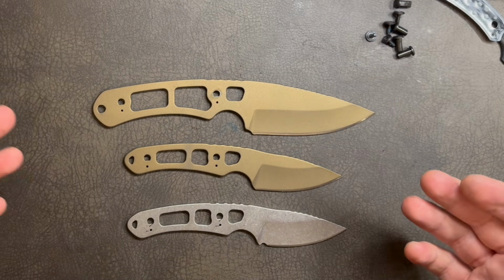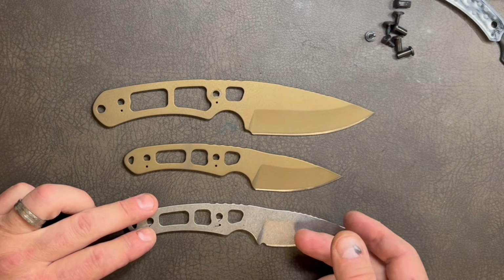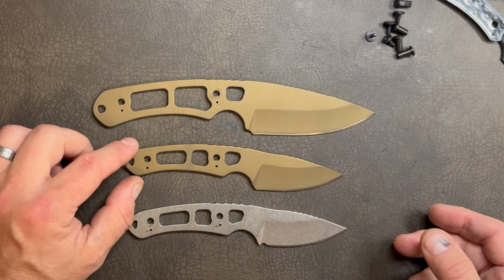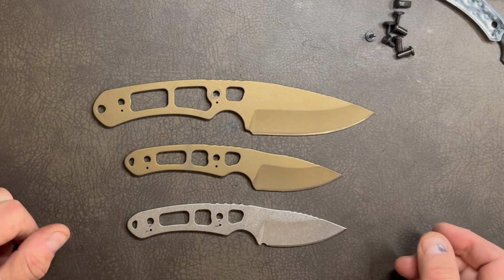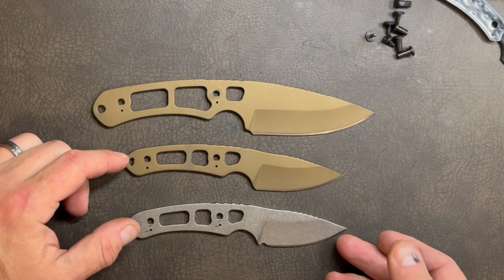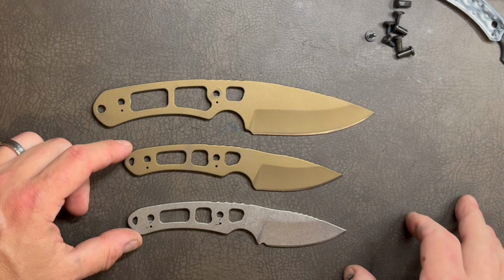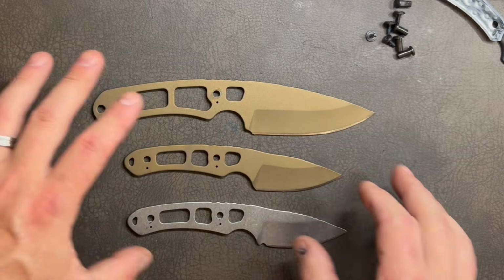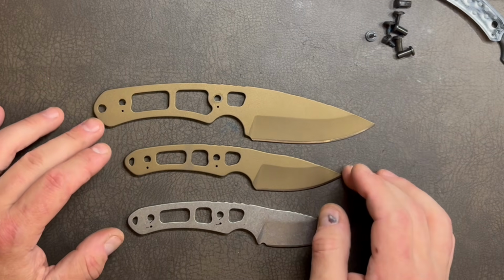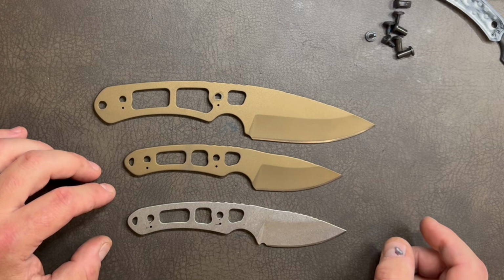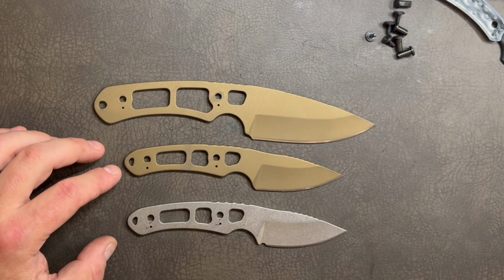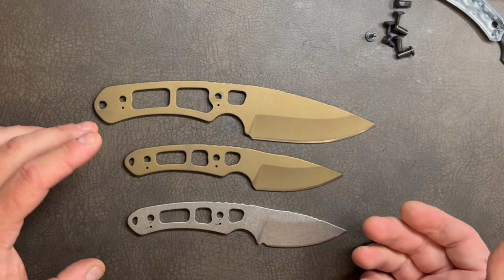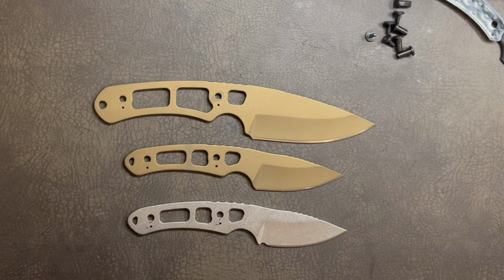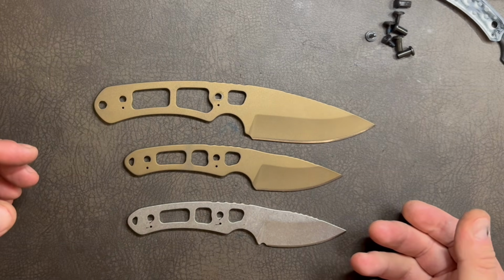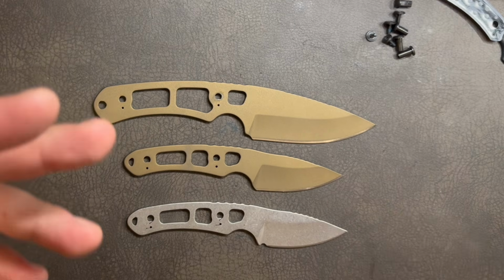Then comes austenitizing, which is what you see in Forged in Fire when they heat it orange hot and then quench. Quenching stainless steel such as 420 HC is very different from oil quenching that you saw in that show, but I don't want to digress too much. Typically, stainless steel blades are placed between 2 heavy aluminum plates to allow them to cool to about 170, 180 degrees Fahrenheit, and then they can be cryogenized, meaning immersed in something very cold. I believe Bos heat treatment that Buck uses requires liquid nitrogen, which is, in my opinion, the only correct way to cryogenically treat the blade.